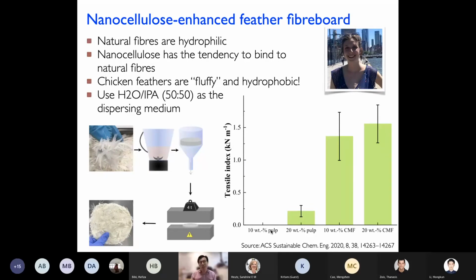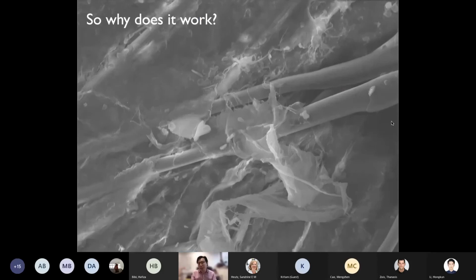So we started with pulp fibers. We dispersed pulp fibers with chicken feathers in a 50-50 IPA water solution, and there's nothing, we can't measure anything out of it. But with nanocellulose here, we are able to measure something out, something rigid, and a significant increase in terms of tensile index. The reason that it works is because the nanocellulose, due to its high surface area, actually encapsulates the chicken feathers rather than binding the individual feathers together.